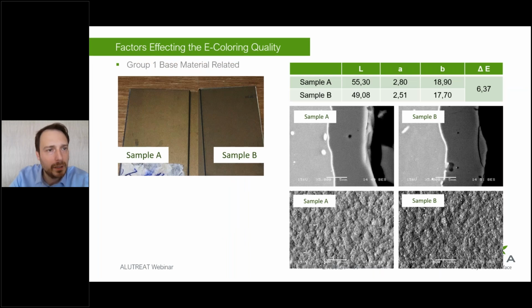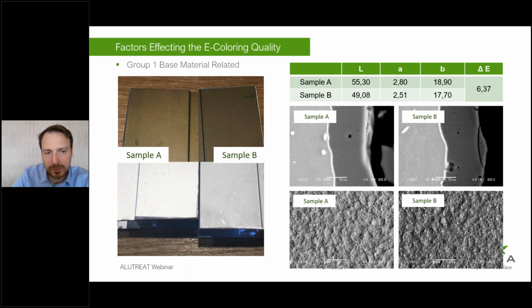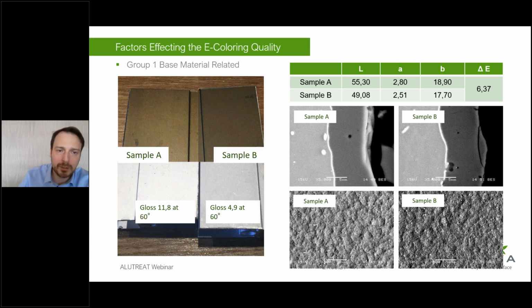So we said we were having problems with samples A and B. Although we have almost the same anodizing and same coloring, the resulting color was very different. And when we said it was very different, we started off stripping the layer and looking underneath at what is happening, and we realized that the gloss was completely different. Therefore, sample A had much more backlight or illumination coming from the anodic oxide, which was making the color appear much lighter. Therefore, the L value was much higher, although the a and b values are very close. So same example, the backlights are dark red. As soon as you hit the brakes, you get the lights coming up. Therefore, the color appears much lighter.